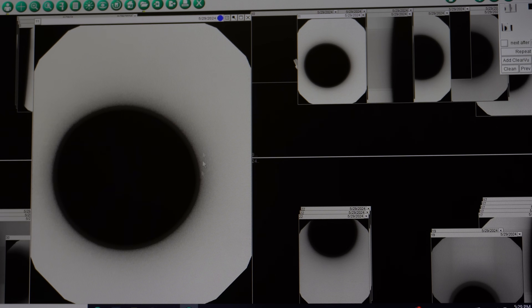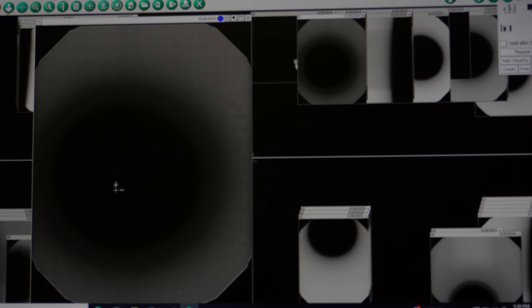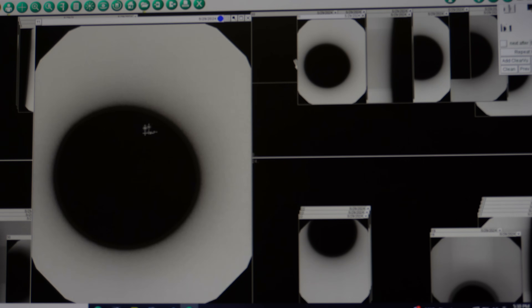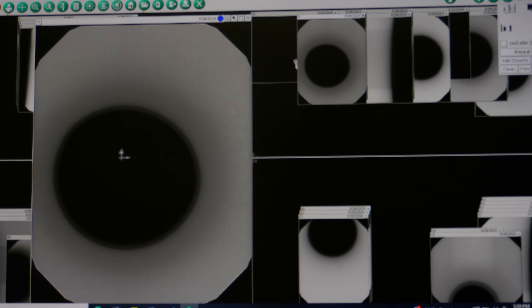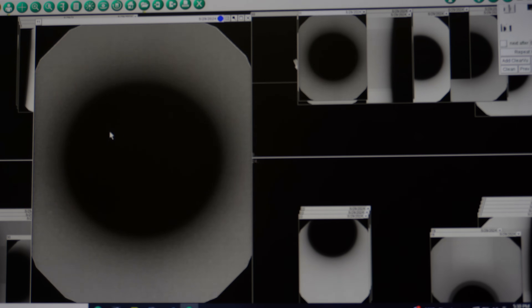Most cracks will happen right around the edge of the hole. That's the part that's under the load, because that's where either the bolt or the clevis pin are going through. The first bolt is the one that tends to have the most cracks. If you're going to find a crack, it tends to be at the first bolt, which is why I was looking at the first bolts in particular. Here it looks pretty good when we adjust the contrast — the metal is uniform, I'm not seeing any cracks jumping out, so we're looking good there.